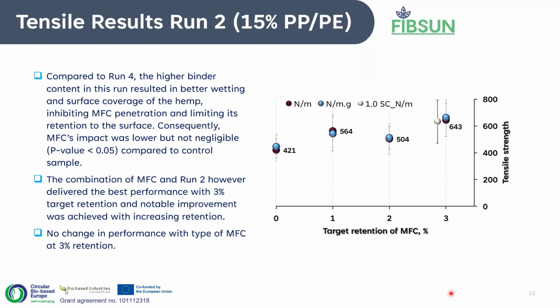But in the case again with 2% and 3% MFC incorporation, we didn't see any real increase. So with run 2, we found that while the initial non-woven has a very high performance, often due to the adequate wetting, which means adequate coverage of the fibers with the bicomponent binder, this coverage becomes more like a limitation for penetration of MFC into the core of the non-woven.